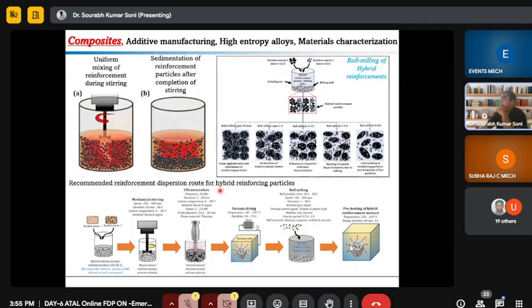So I went through around 500 to 600 research articles, and then I prepared this dispersion technique. Not very rigorously. We can use a very small duration. We can vary the duration, and we can achieve the dispersion. Here, this one is reinforcement 1, reinforcement 2, and we will mix them in acetone. Then we will perform mechanical stirring. I mentioned the process parameters also, and we must follow the process parameters according to the reinforcement material. So I have mentioned the range you can use for your materials.